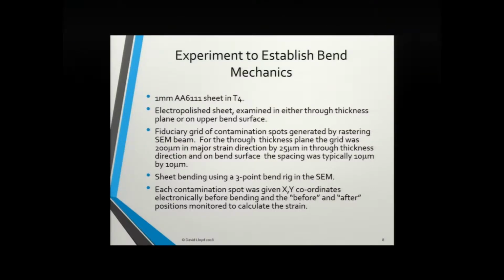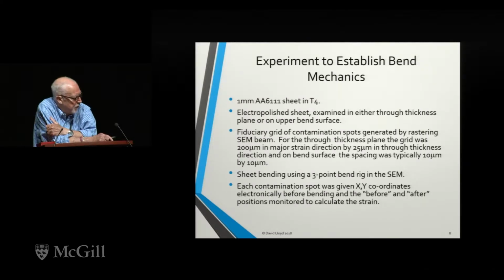So we decided to do some experiments that would give us an idea of how these equations work. We've done experiments on a whole variety of alloys, but I'm just going to talk about experiments on 1 millimeter sheet of 6111. It's in the T4 temper, and it was water quenched sheet. The sheet was then electropolished, and we examined either the through thickness plane or the upper bend surface. And what we did was lay down a grid of carbon contamination spots. We did it in the SEM by rastering the grid along and basically letting it dwell at various points. And that gave us a grid of carbon contamination spots.